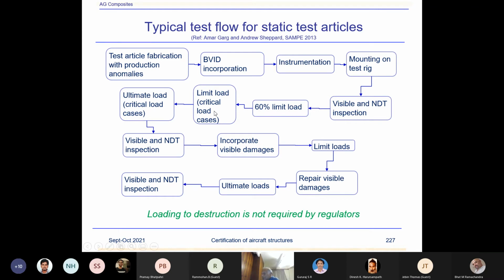Various load cases. There could be 3 cases or 4 cases critical, like one could be torsional critical, and there could be bending critical, or a third one could be another load critical. So critical load cases are applied. And then, though I've not shown it over here, you will inspect the parts just to show that there's no permanent deformation, because that's a requirement when you are applying the limit load. There should be no permanent deformation to any of the structure like metallic fittings. So at every step, in fact, I have not incorporated it over here, there would be NDT and visual inspections for the whole of the structure. So basically inspections at every step.